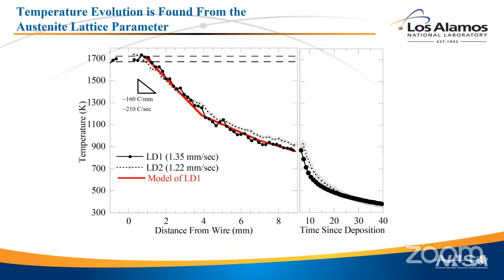It drops down, and at 9 mm or so, that's when we turned off the welder. So now it starts cooling more quickly, but it's not rotating anymore. So now it's just time that changes. So you can see the temperature drop as distance from the weld. And then again, we turn it off and you see it quench because you're not adding any more heat. We did it at two different deposition rates if you want, and they actually fall quite close together. They're a little bit different. They go in the direction you would expect.